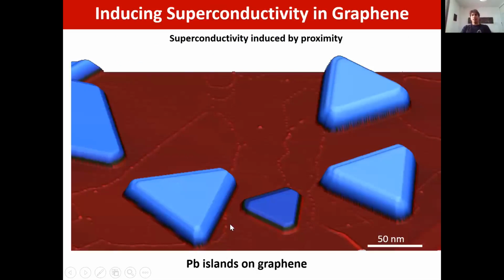And here is how we had in mind to induce superconductivity. We had in mind to use the proximity effect. So we deposit lead, which is a superconductor below 7.2 Kelvin. So we have this very nice lead island that grows on the surface. We knew this because of our French colleagues, Pierre Mallet and Jean-Yves Veuillen. And here we can see how the lead island grows, this very nice triangular lead island.